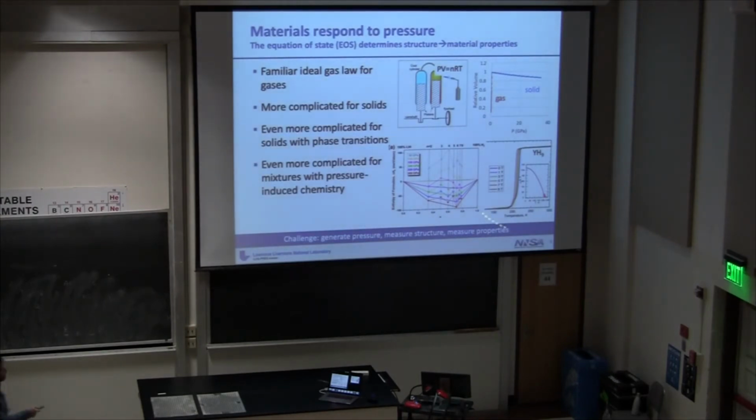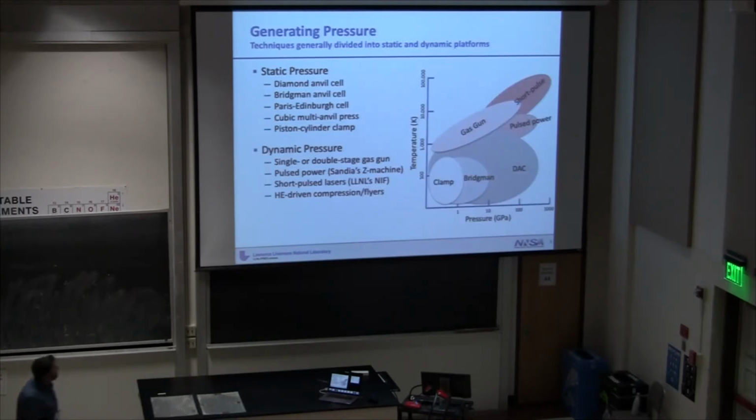And then one of the exciting things that happened was these superhydrides of yttrium here, where you can see superconductivity up around 200 Kelvin at high pressure. What these polyhydrides or superhydrides are doing is basically allowing you to access the purported superconductivity of metallic hydrogen, but at a slightly lower pressure. These are still very high pressures. This is probably up around 100 GPa or something like that, maybe 200. Cool.